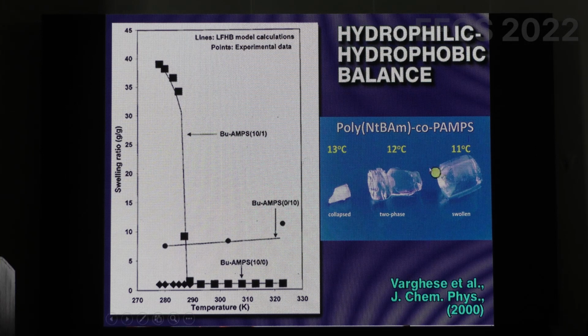But if you form this copolymer at a very exquisite composition of 10:1, 10 of the hydrophobic, 1 of the hydrophilic, this polymer has a wonderful phase transition. In fact, this is the copolymer, this is a collapsed state, the swollen state, and at 12 degrees, you can actually see a coexistence of both phases, the swollen and the collapsed. So this is really and truly a thermodynamic phase transition, and it's so subtle, it's so beautifully subtle.